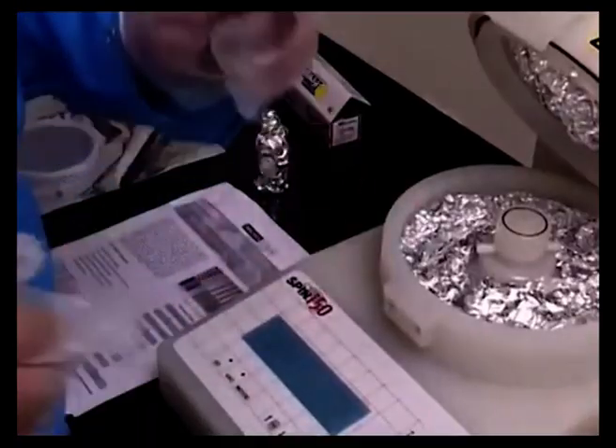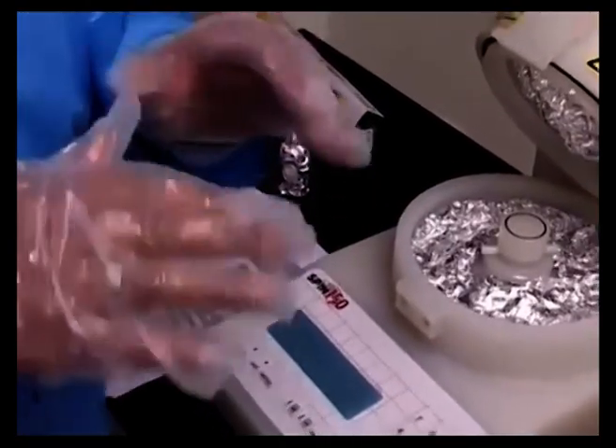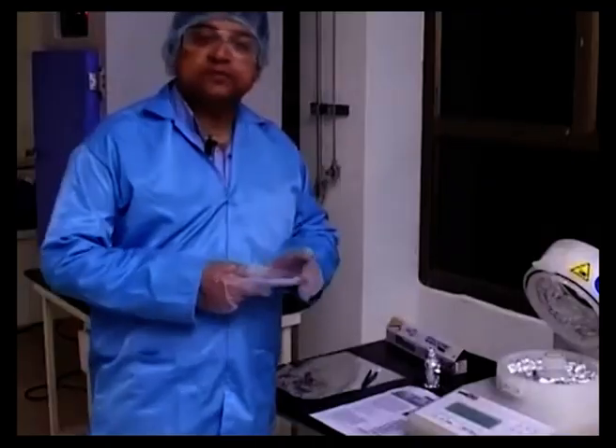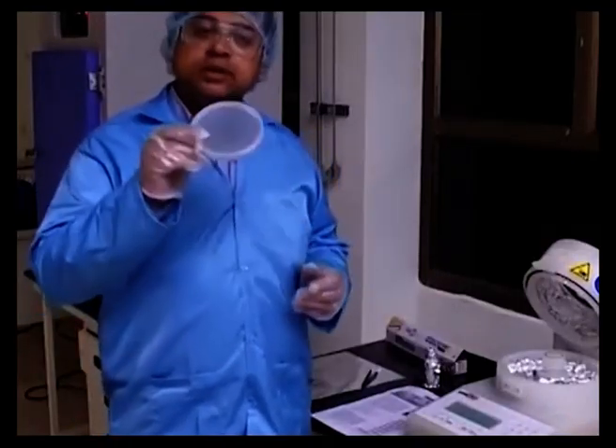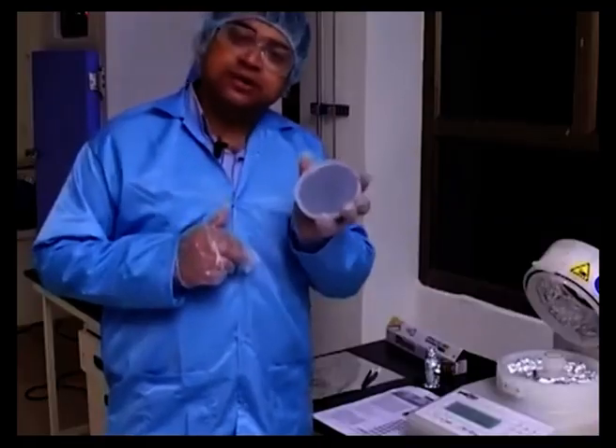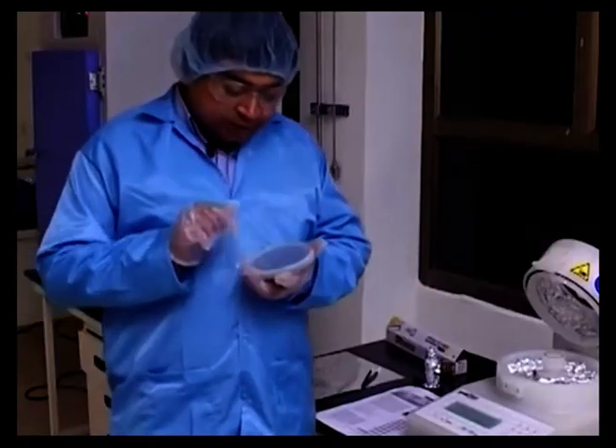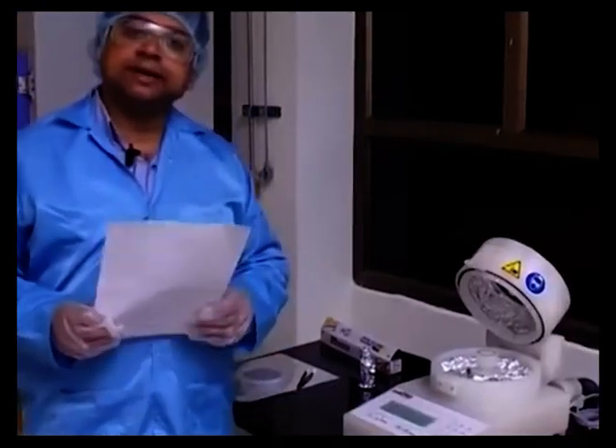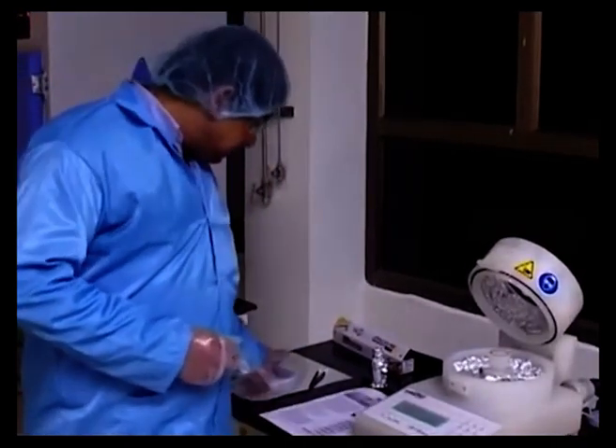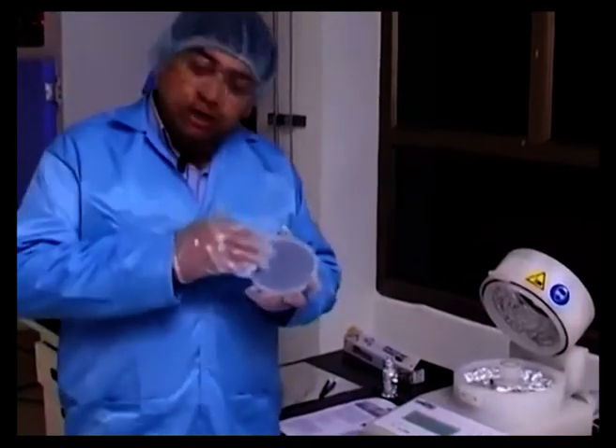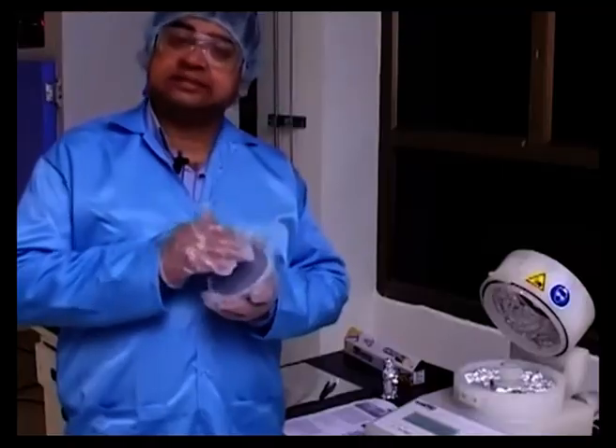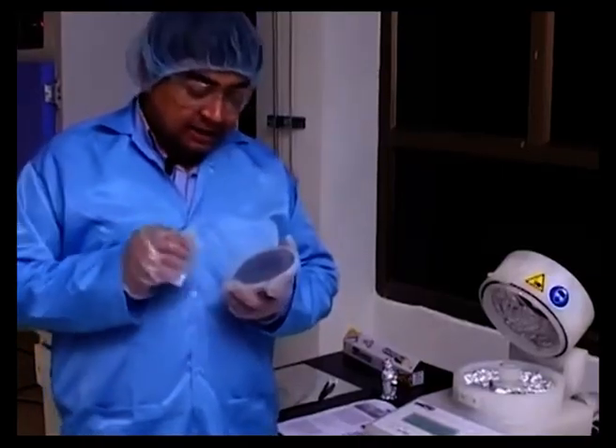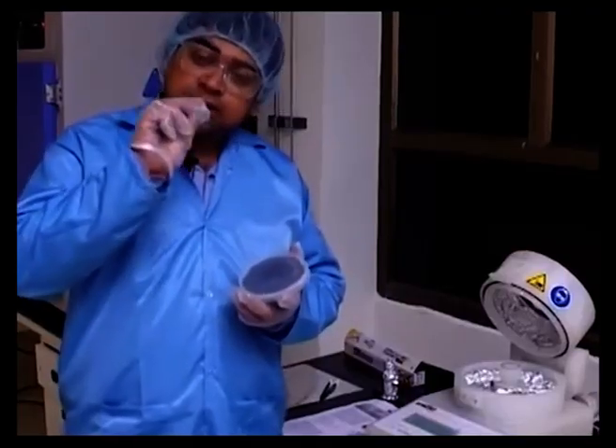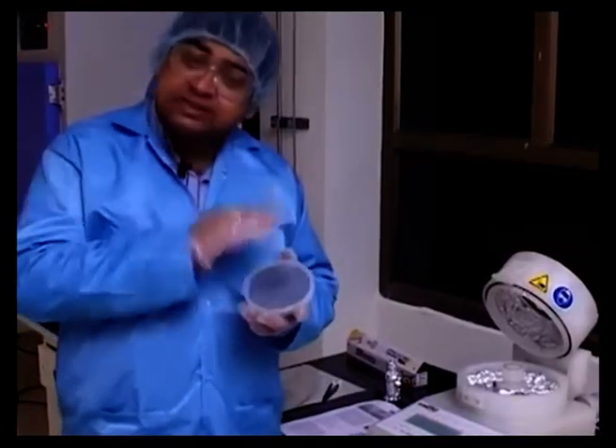When we are talking about a circular wafer, what is very important for us to understand is that the resist that you are putting should be sufficiently covering the wafer. What we are doing is spinning the resist on top of this circular wafer, which is about 4 inches, and the spinning operation should be able to adequately cover the whole wafer surface. The goal here is that the resist should not have any gaps or any islands on the surface as you are spin coating it.